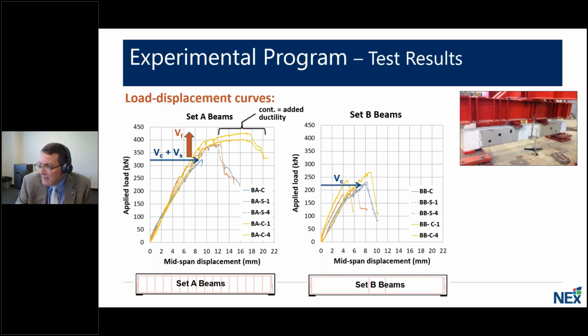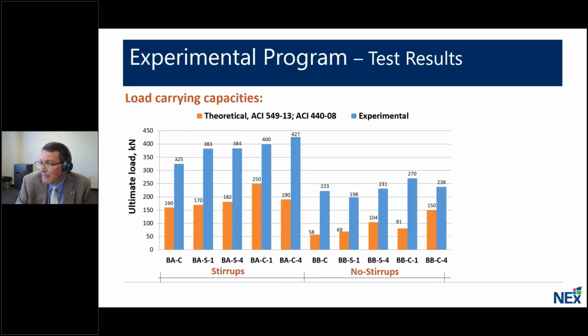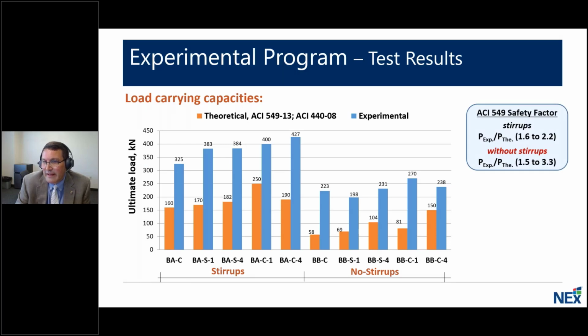If we look at set B, the only contribution we have here is that of the concrete, and then the addition of the reinforcement from the fibers. For set B, without the presence of the internal steel reinforcement, we see that the FRCM strengthening system is much less effective in this experimental lab work, which was a major takeaway from this work. As shown here, the current ACI design predictions are all very conservative.